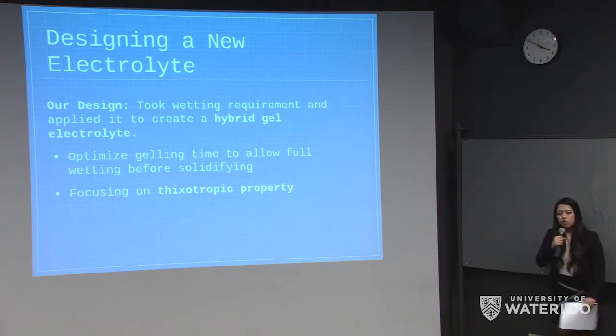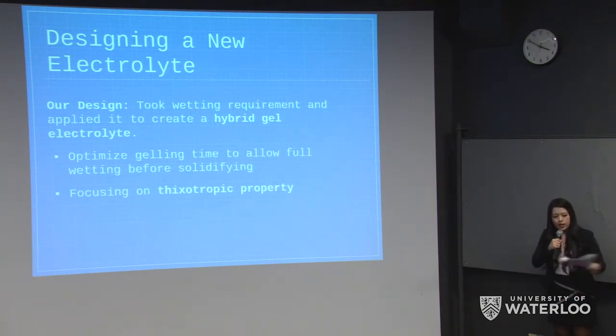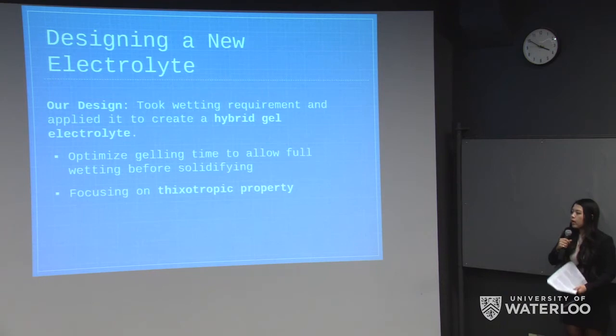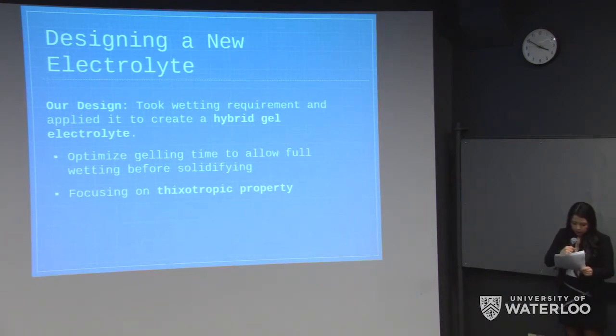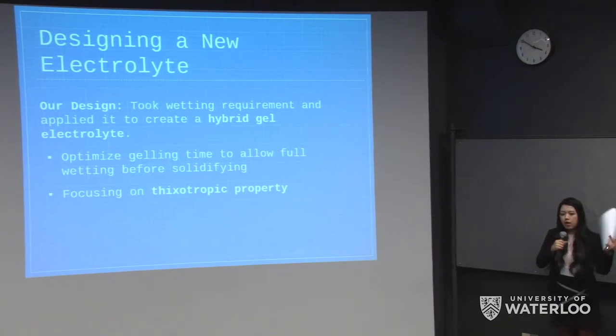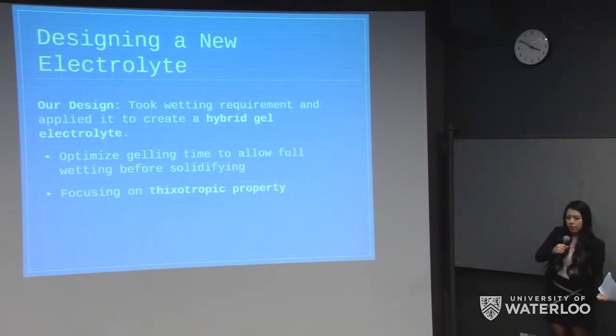So we wanted the electrolyte to be liquid-like when first poured onto the separator. And we wanted it to stay liquid long enough for it to actually wet the separator and be absorbed. But then we wanted it to become a gel afterwards, because we desired the gel-like properties where it wouldn't leak out of the battery. So this is why we termed it hybrid, because it's both liquid-like and it can transition into solid-like.